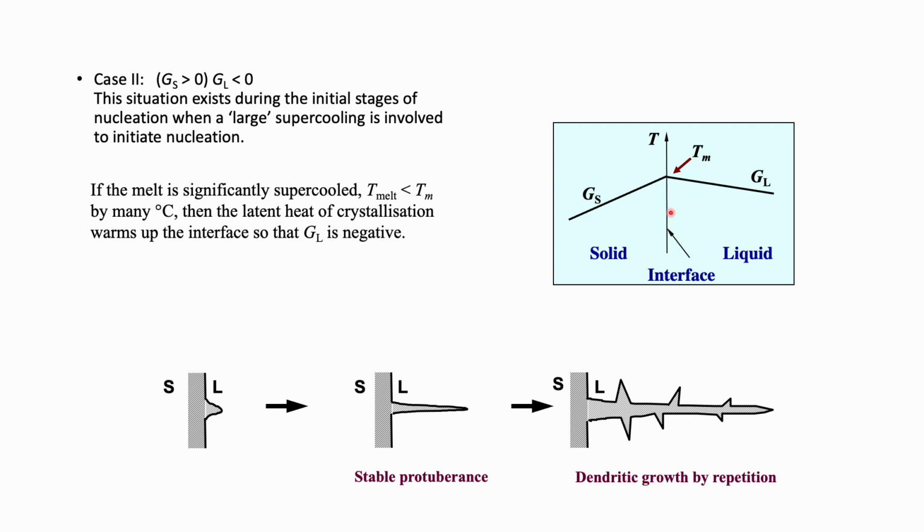Now, in the liquid phase side away from the interface, the temperature is lower than at the interface. That's why it is possible for a tip to go to a deep position in the liquid phase side, because the temperature here is lower than at the interface position in the liquid phase. Then this tip can go further, and can also grow in other directions, as long as the temperature in this region is below Tm. Of course, going further into the liquid phase side, the temperature will go higher again. That's the reason that when you have this kind of temperature distribution in the liquid phase and solid phase, you have the opportunity to produce a grain shape like this. This we call the dendritic structure.